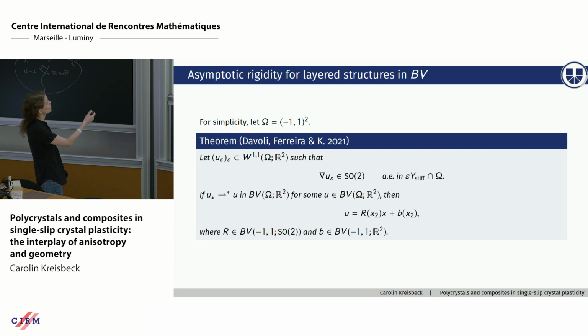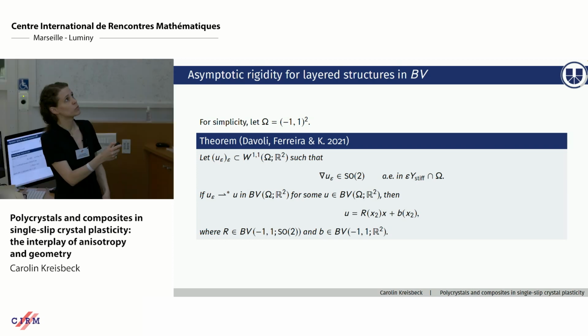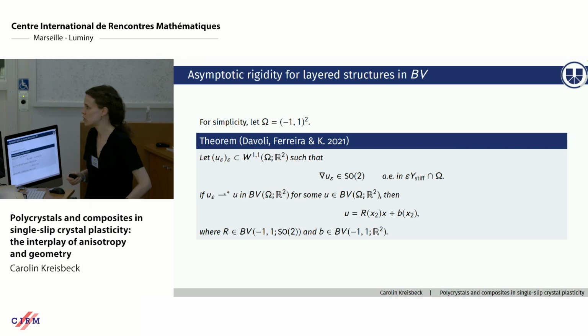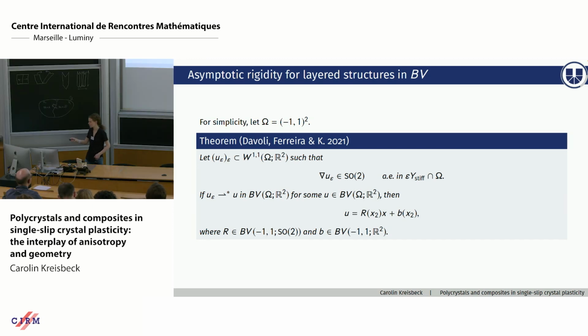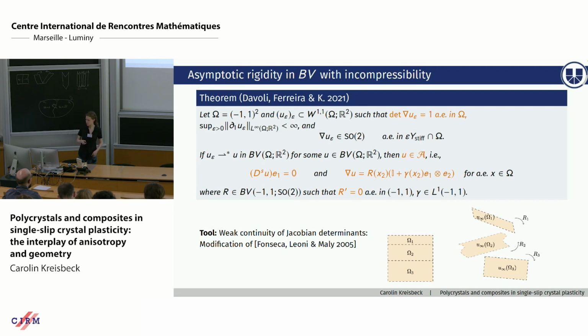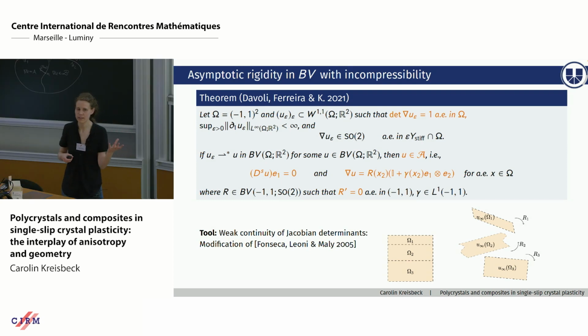Precisely, we start off with a sequence in W^{1,1} so that the gradient of u_epsilon is in SO(2) on the stiff parts, and we converge weakly in BV. And then we recover again the same structure of the limit deformation as before, just now R and b are BV functions. Now we need to incorporate incompressibility to get a refined asymptotic result. We do that by requiring the determinant of the gradient of u_epsilon to be equal to 1 almost everywhere, and we suppose on top of that that we have uniform control on the first column of the deformation gradient in the L infinity norm.